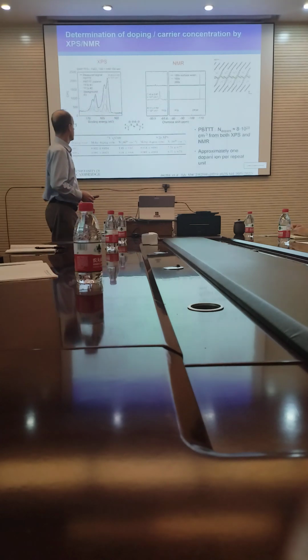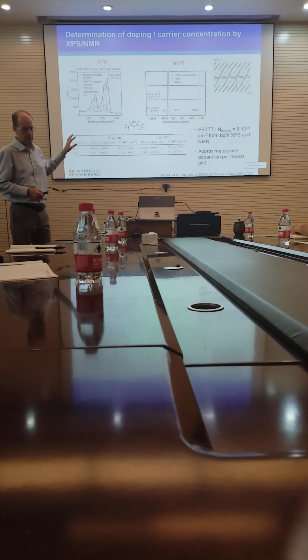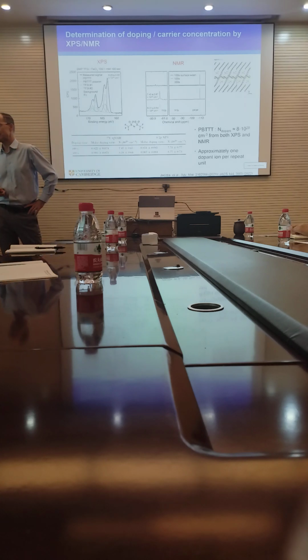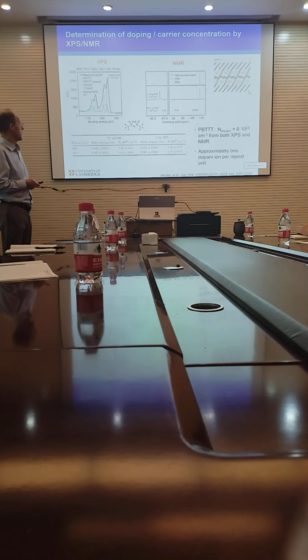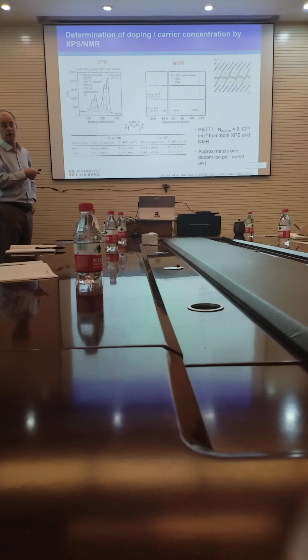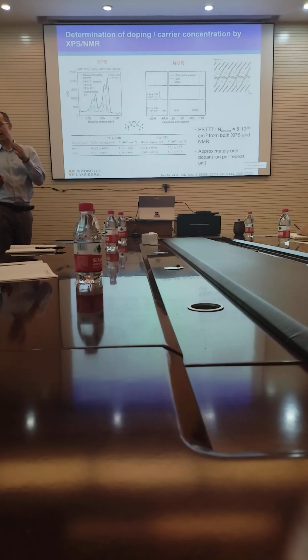Before I discuss it, I want to explain briefly how we determine the doping levels. A simple way to determine the doping levels in a system like this is to do XPS. If you look at the sulfur core level, the polymer PBTTT contains sulfur. The dopant, in this case TFSI, contains sulfur. These two sulfur components are chemically shifted in XPS. So you can see one component here due to the dopant counterion, and the other component here is due to the polymer, and then you can determine essentially how many dopant ions you have per repeat unit of the polymer.